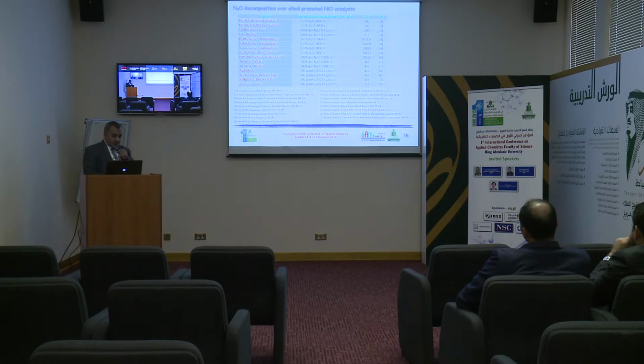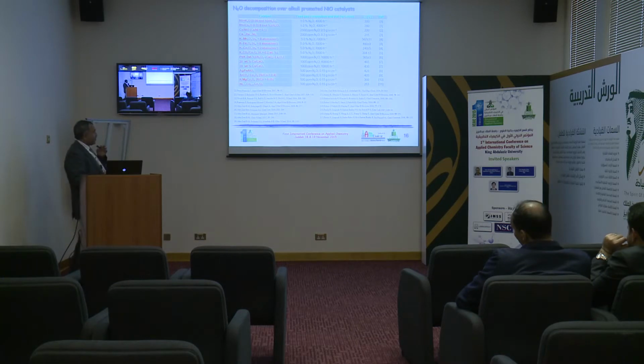Comparing our results with some other results reported in the literature, I am trying to use the cursor to let this section show the results. The last 4 or 5 rows in that table show the activity data carried out on some other catalysts using the same conditions. So we can see that the T50 values of our new catalyst are really within the same range, or maybe sometimes better.